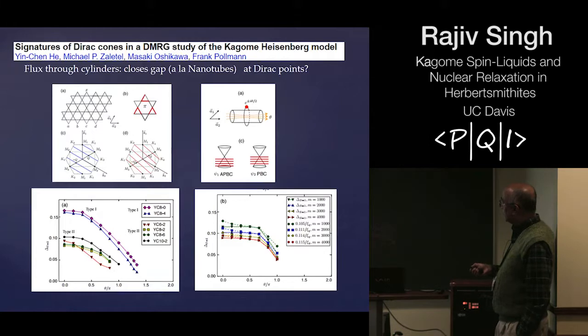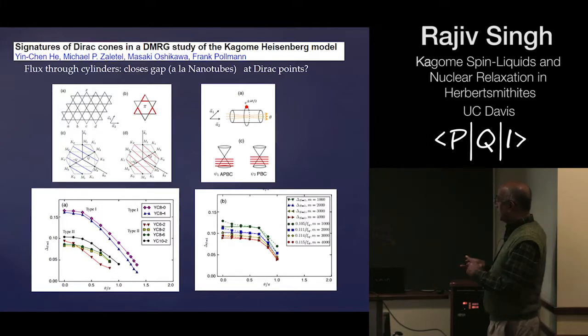What these authors argue is that the reason why DMRG has been seeing a gapped spin liquid is because they are looking at this very special geometry of a cylinder. So if we remember from the study of carbon nanotubes, a Dirac spin liquid is supposed to be a system where you have Dirac cones. In other words, in momentum space, there is a particular point where you have gapless excitations. Maybe 2 points in momentum space in the Brillouin zone where you have gapless excitations. But if you fold the system into a cylinder, then the allowed momenta are only along certain lines, and those can miss those special points, depending on how you fold them. And then if you miss those Q points, then of course you are going to see a gap.